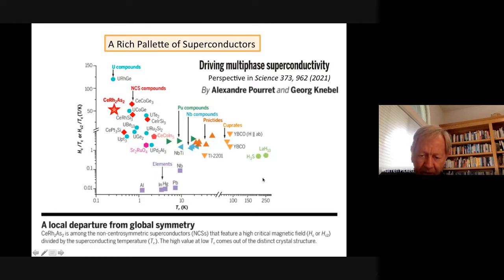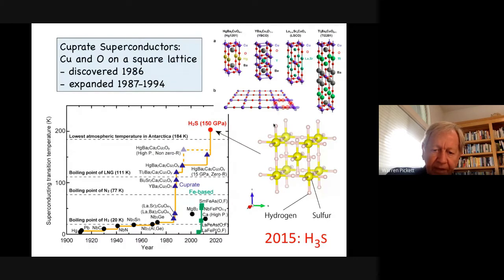Two were known at the time this plot was made by these two gentlemen. And there's quite a variation in this ratio. You can see it's a log plot. So that's one of the interesting broad issues in superconductivity. Okay, back to this plot and the new discovery in 2015 of H3S, hydrogen 3 sulfur, not 2, but 3, at 200 Kelvin. And then lanthanum hydride up here at 260 Kelvin in 2018 or 19, not shown here.